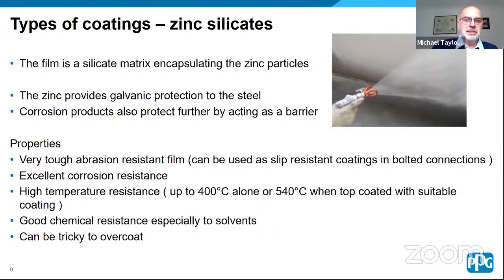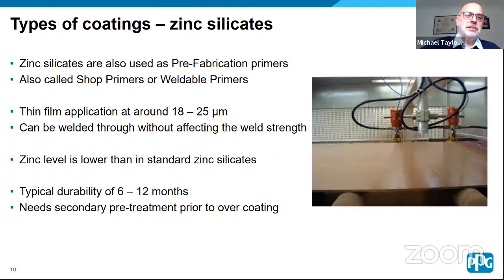One thing with zinc silicates is they can be tricky to overcoat, and I've got a few comments on that later on in the presentation. Another area where zinc silicates are used is as prefabrication primers. They're also known as shop primers or weldable primers. These are typically applied on an automatic line, as shown in the picture alongside. Typically thin film applications, 18 to 25 microns, and you can weld through that coating without affecting the weld strength or any of the properties of the weld.